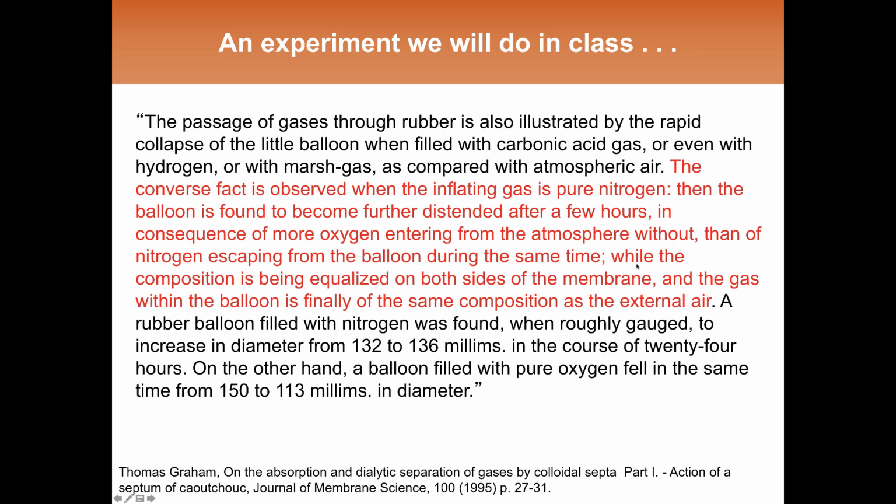And this would continue until the composition of gas inside and outside the balloon would be equalized, and after that the nitrogen-filled balloon would shrink. And he also noted that a balloon filled with pure oxygen would simply deflate at all times during this experiment. And so we'll do that experiment in class and connect your experience here back up with that in Graham.